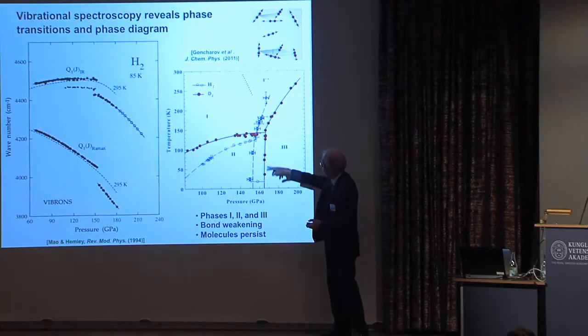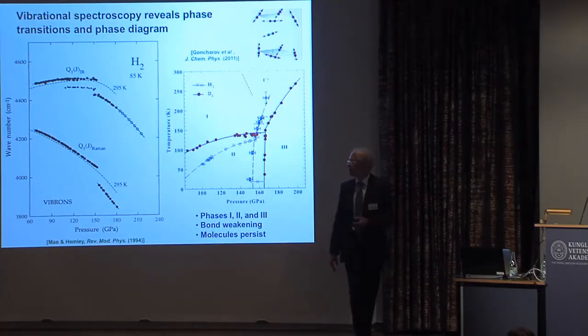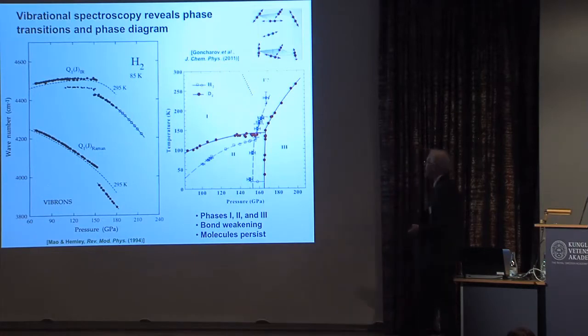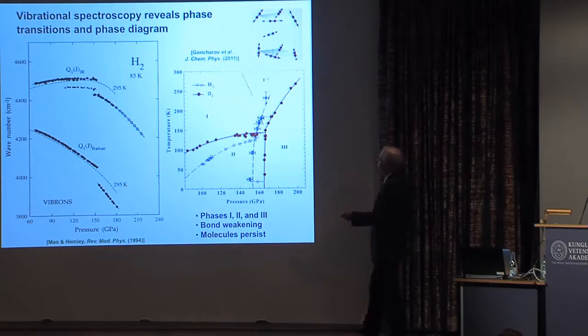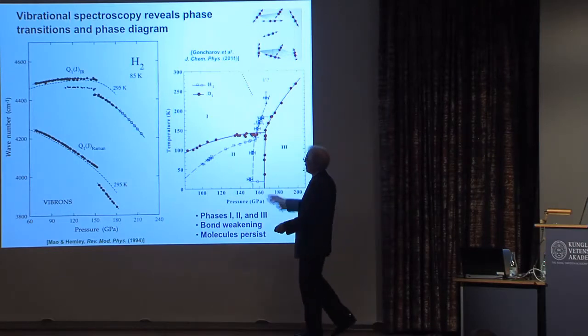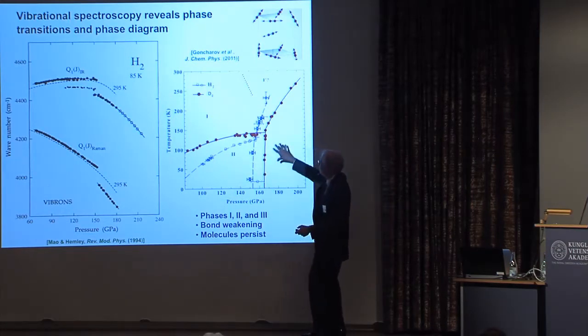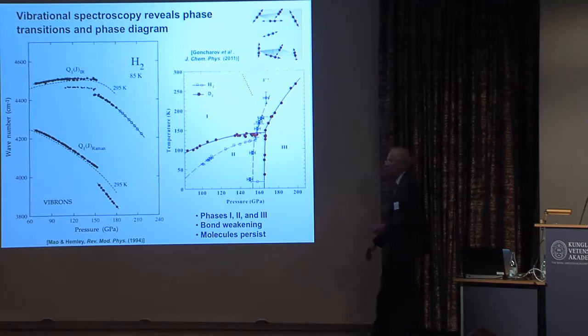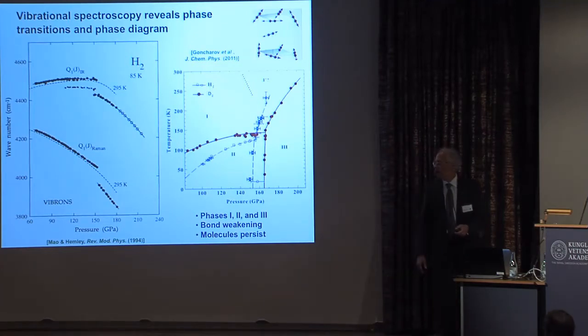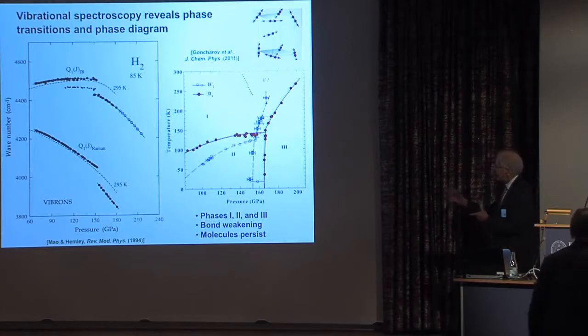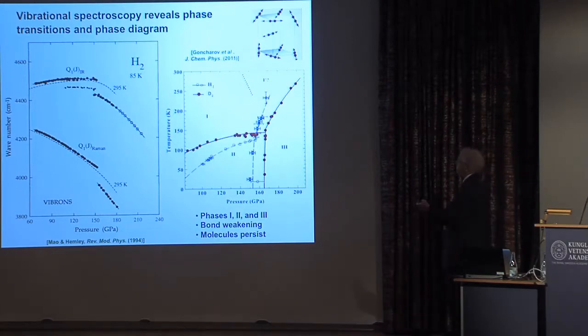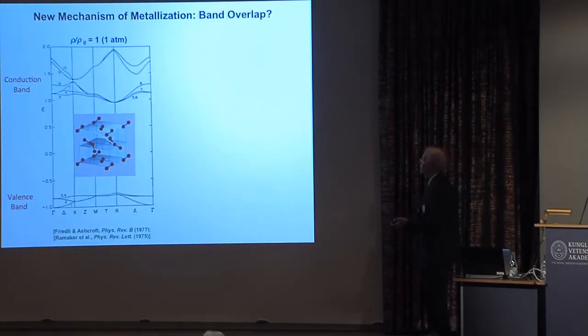And these are diagnostic of phase transitions in the solid. So you can map this out as a function of P and T and map out the phase diagram here up to roughly 200 gigapascals or 2 megabars. And you can see there's phase 1, which we know is HCP. There's this other phase, phase 2, and phase 3, meeting at a triple point. This was worked out a number of years ago, and you can see a slight isotope effect depending on whether you have deuterium or hydrogen.